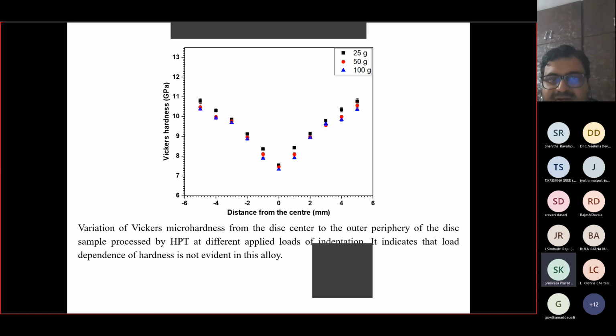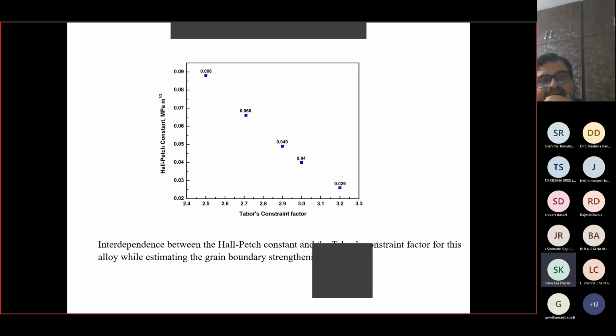And the hardness shows that you have very high hardness at the edge and somewhat lower at the center, and that comes from the strain variation that you apply during this torsion. Also, when we measure the hardness at different indentation loads, in this case it doesn't show any indentation size effect. That is, the decrease of hardness with increase in load that we have seen in other systems is not seen in this system. There is a reason for it. Also, the Hall-Petch constant that we evaluated to understand what exactly is happening is very low, and that accounts for the grain size softening. That is, you have grains of about 8 nanometers and 12 nanometers, which is close to 10 nanometers.